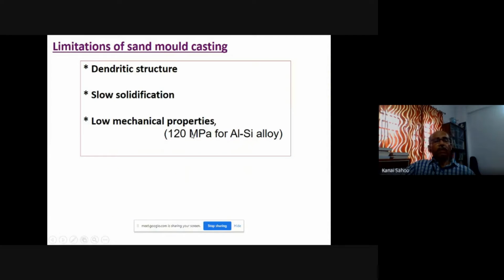But still, the limitation is that sand cast has very low mechanical properties. For example, aluminum silicon alloy, 120 MPa. Note this value, because you will see at the end or the middle of my talk how this 120 MPa can be enhanced several fold. I'll always take aluminum silicon as the example, and show you how, by changing the process parameters, we achieve both strength and ductility. One simple example I have highlighted in my talk.